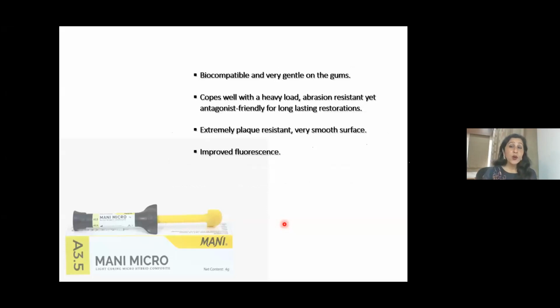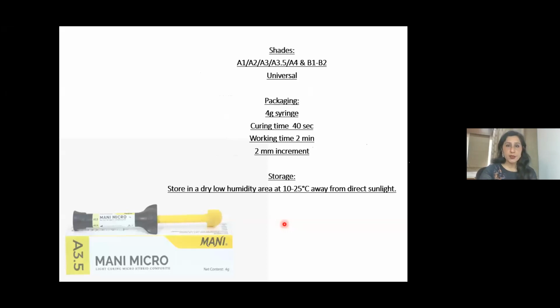And also one more thing, that they have very good improved fluorescence, and this is what you want if you are doing your anterior restorations. So they give you a good fluorescence as well, and they are extremely plaque resistant, give very smooth surface. Now they are available in a variety of shades, and they also come in universal shade. If you want only one shade, that is also available. The curing time is 40 seconds, working time is 2 minutes, and for a 2 millimeter increment. So remember, you have to take no more than 2 millimeters, a 2 millimeter increment to be taken for